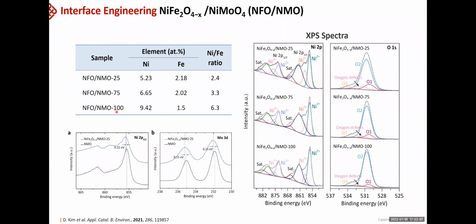The presence of the nickel 3+ species suggests there's oxygen vacancy formation. So from this high resolution XPS data that compares the three species, we can see that the nickel 3+ species is more on the smaller ones than the larger species. And also the oxygen defective sites are more on the smaller ones. So you can consider that the sample with the smallest catalyst size has the maximized nickel 3+ species and oxygen defect sites.